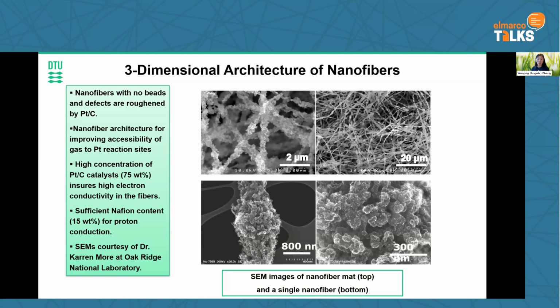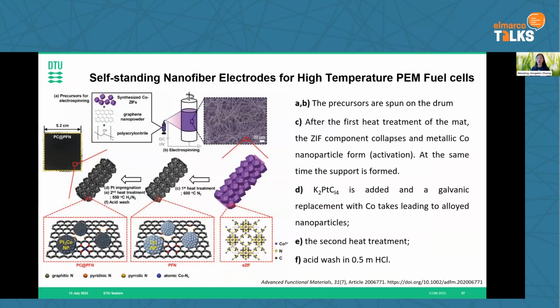reactions. Now at the DTU, we are working towards another type of fuel cell, a high temperature PEM fuel cell, operating at around 160 degrees Celsius. So here we look at the self-standing flexible nanofiber electrode. What we did is put a metal organic framework into the polymer, do electrospinning, and then carbonization. By galvanic replacement, we can exchange cobalt with platinum.